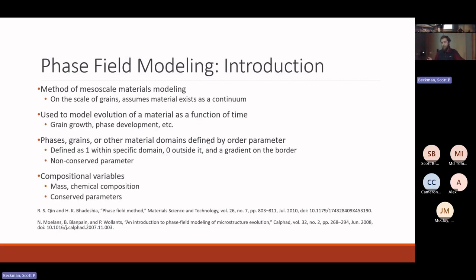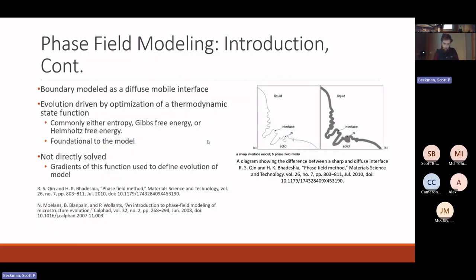This is a non-conserved parameter, and what I mean by that is how much of this domain exists in the system will change as the model progresses. This is different from something like a compositional variable such as mass or chemical composition, which is a conserved parameter and does not change across the system as a whole as a function of time.